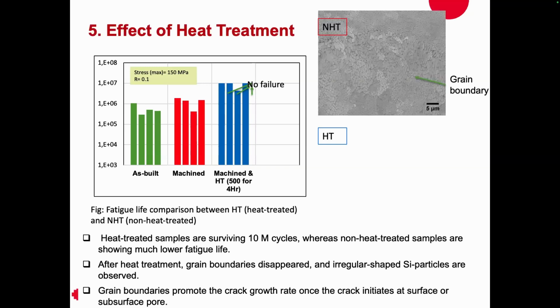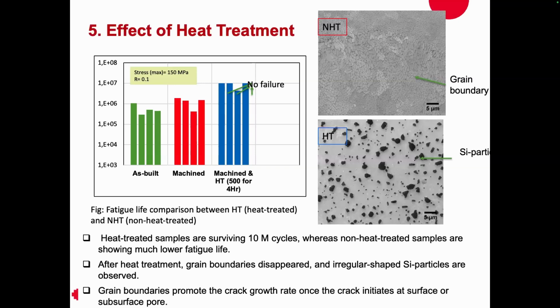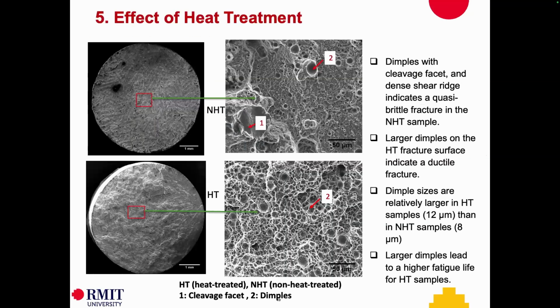And this is again due to the grain boundary. No heat treatment has fine grains. If you have a heat treatment, in this case, we find it exposes a lot of silicon particles. So grain boundaries promote the growth rate once the crack initiates at the surface and subsurface pores. Once the crack initiates from the surface, finer grain boundaries promote the growth, while if we remove them, the hardened silicon particles will slow down and resist the crack growth. So this is what the heat treatment is causing, the difference.